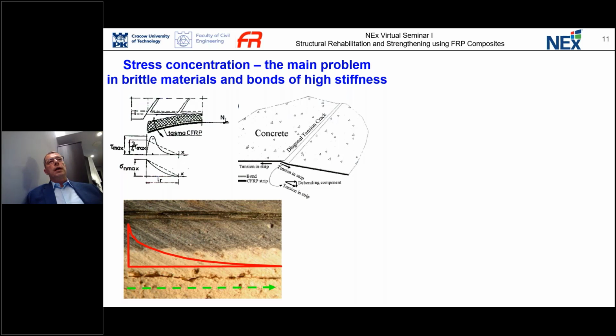One of the most critical sources of damage is stress concentration. When we use brittle materials, high stiffness materials, we have a stress concentration problem. This appears mainly in the places of cracked structures, but also in the bonding area where the high stiffness composite material is bonded to a very weak substrate. In this case, stress concentration causes microcracks, then a main crack, and the structure goes to failure. So how to solve and manage this problem?